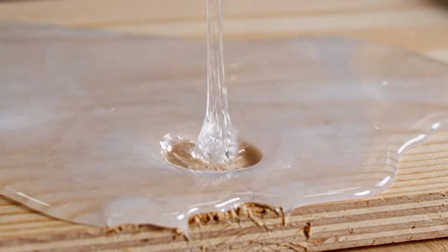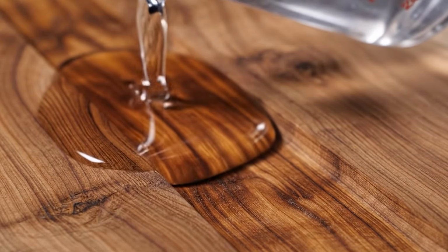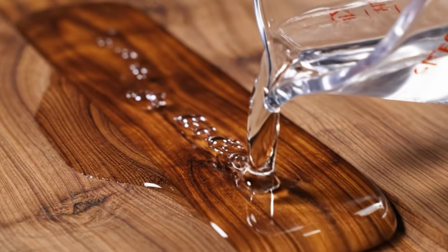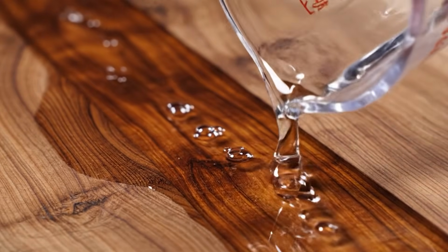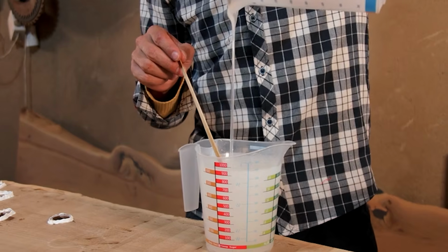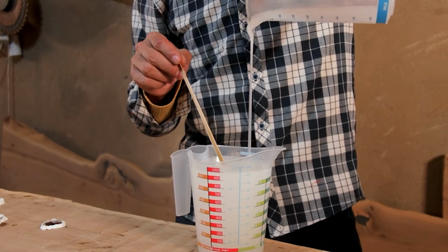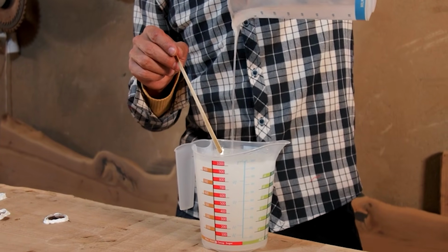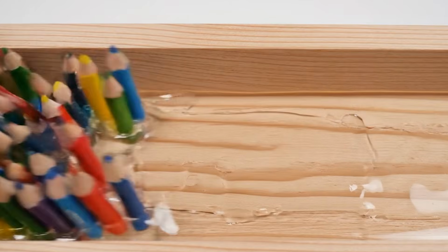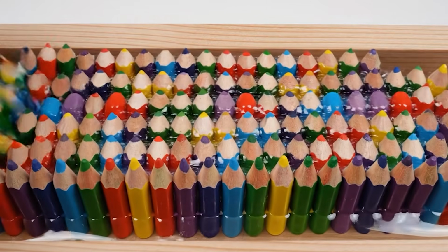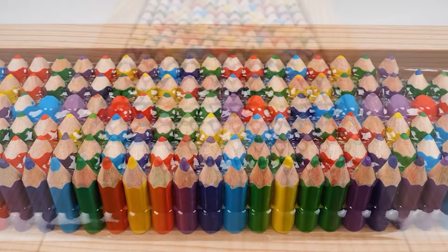Pour a thin seal coat into the river channel first, about 1/4 inch deep. This seals the wood grain and helps prevent air bubbles from leaching out of the wood during the main pour. Let that seal coat set up for about 4 to 6 hours until it's tacky but not fully cured. Then stand your pencil segments upright in the tacky epoxy, packing them in tight.